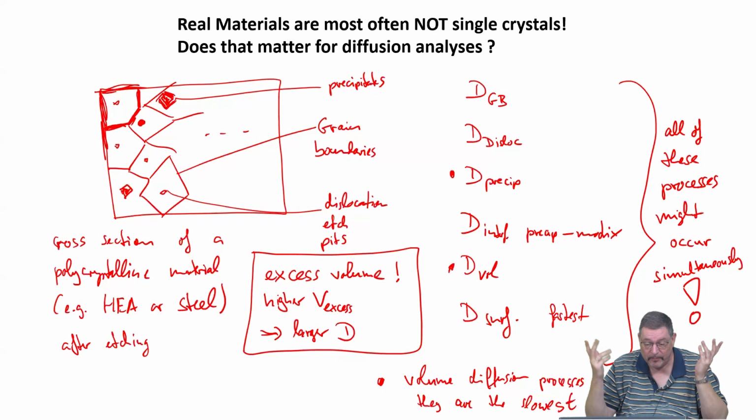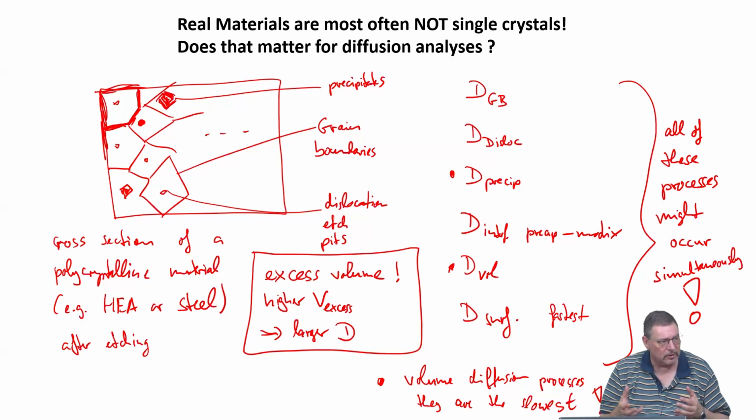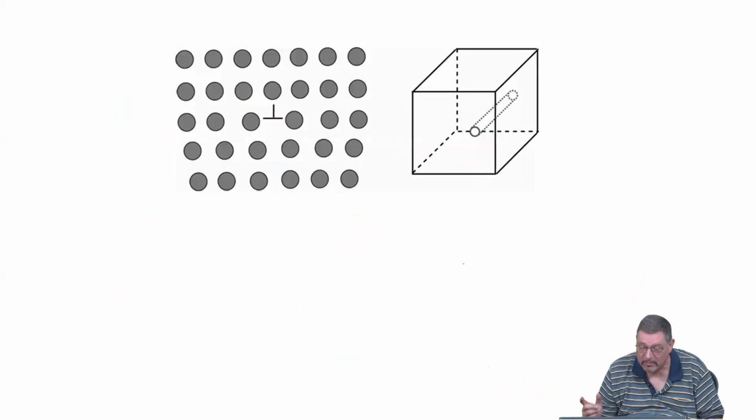And this is a very nice mental picture, and actually one can show by computer simulations, there was just a paper last year, that this can actually be done in a quantitative way. So you can derive a model, a computer model for diffusion in grain boundaries, which is just parameterized by the excess volume present in a specific grain boundary. So it's a mental picture that is really rather accurate, which many mental pictures are not.